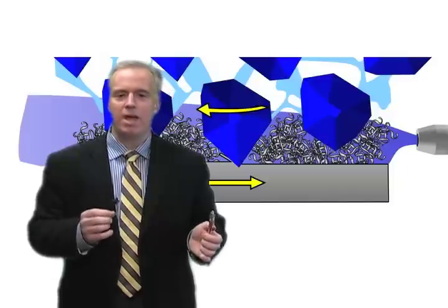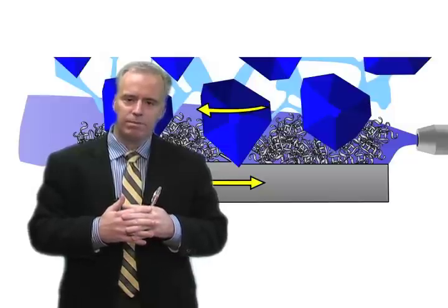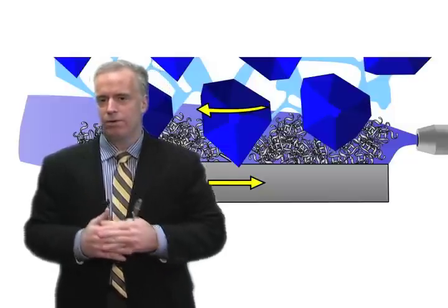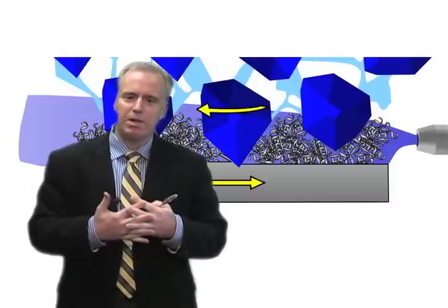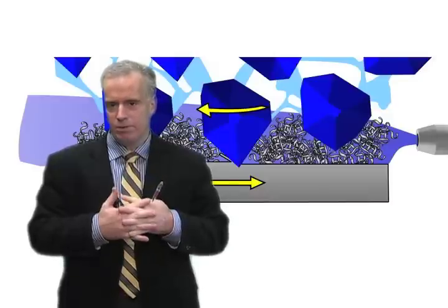Aluminum oxide is Al2O3. They're mutually soluble in one another, the Cr2O3 and the Al2O3. So they'll sort of chemically react or dissolve away in one another. That's just a nasty chemical reaction between the two.